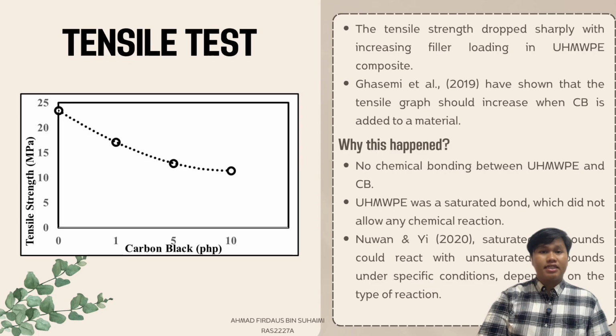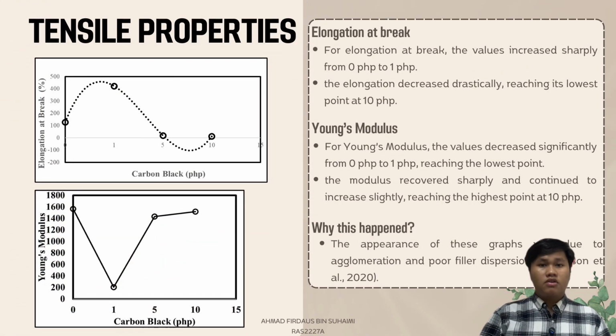Okay, for tensile test, the tensile strength drops sharply with increasing filler loading in the ultra-high molecular weight polyethylene composite. Why did this happen? This is due to no chemical bonding between ultra-high molecular weight polyethylene and carbon black, because ultra-high molecular weight polyethylene has a saturated bond which does not allow any chemical reaction. For tensile properties, the elongation and the Young's modulus show the opposite trend. This is due to the agglomeration and poor filler dispersion.